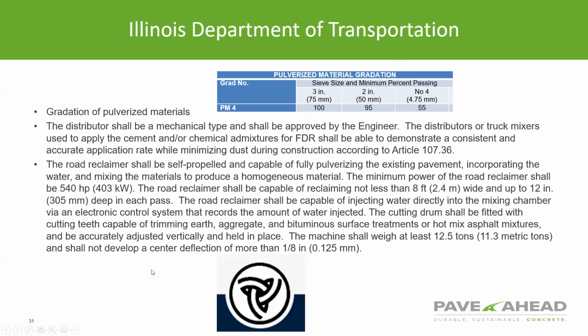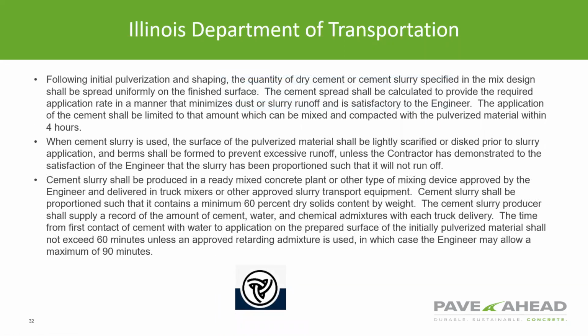And I'm not going to go into detail, but what you can find is here, of course, a gradation for the pulverized material, specification on the reclaimer itself, process, specification on the slurry process with some limits, a minimum 60% dry solids content by weight is in the specification, and a time frame of 90 minutes after first contact. The material needs to be applied to the surface. So it's a very comprehensive specification if you'd like to go online and look at that.